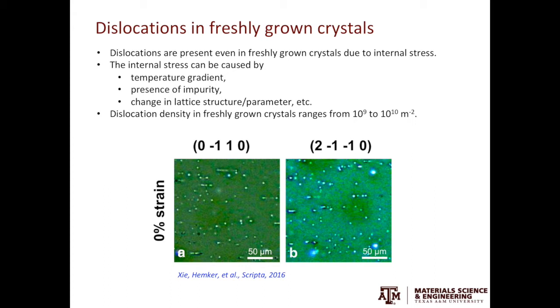Let's look at the micrographs down here. Those are optical images of a magnesium single crystal before any deformation. In both micrographs, you can see those speckles. Those speckles are etch pits from dislocations. These micrographs offer strong experimental evidence that dislocations are present in crystals even before any plastic deformation.